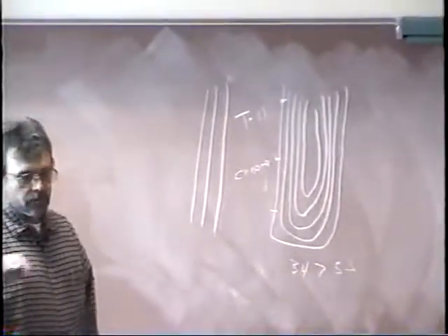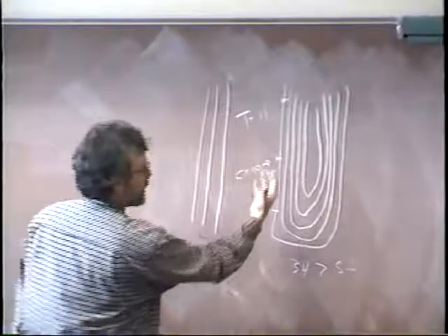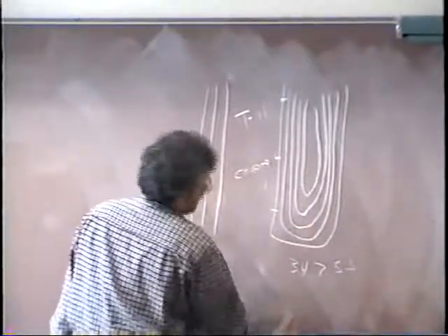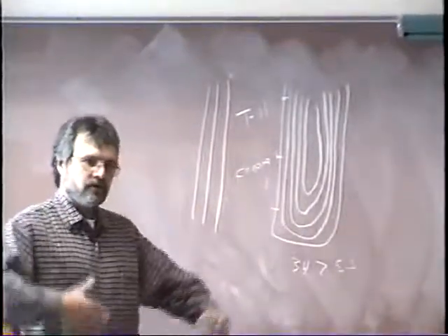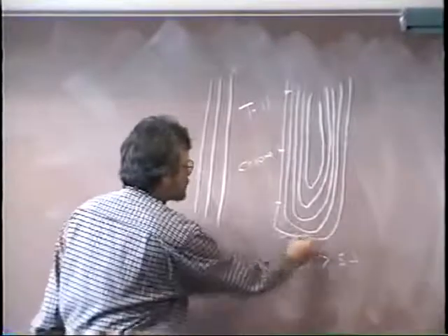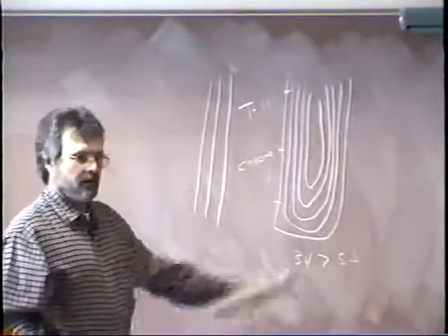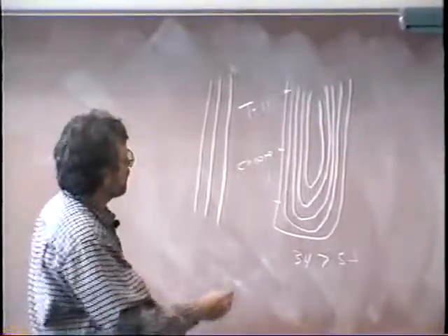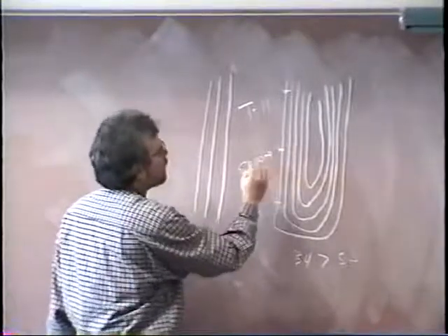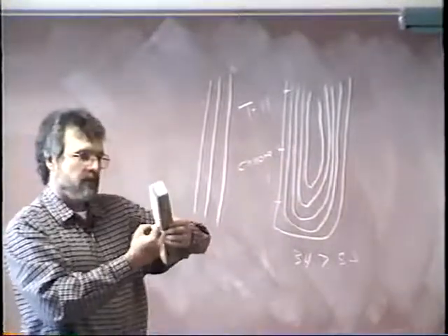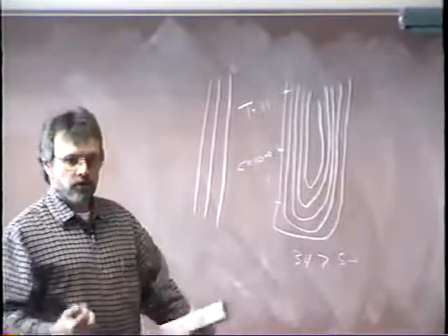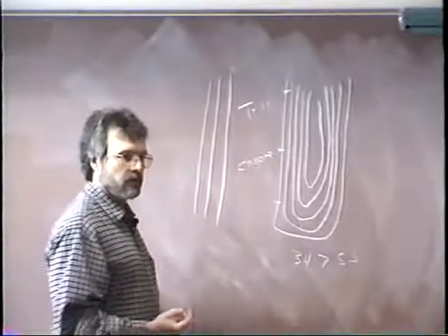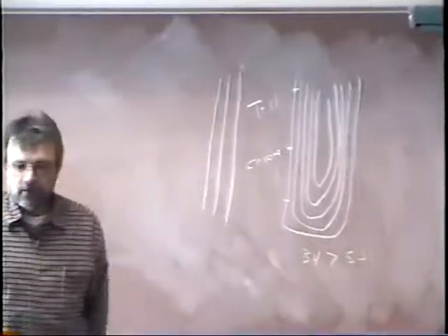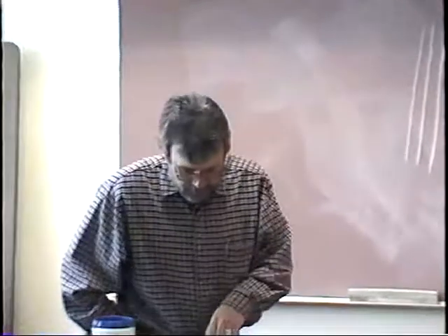But because chrome moly resists creep, the weight of that hanging down there inside a boiler where there's an open flame and you've got pressure inside this and steam up to 2,000 pounds and more, the chrome moly steel helps to keep it from stretching and failing under those stresses. And that's the purpose of the chrome moly. Get those characteristics in there.